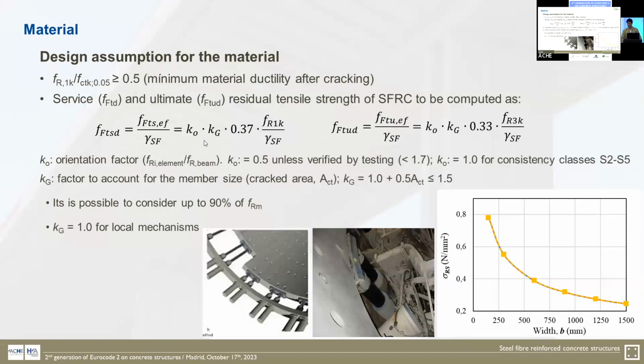And we also have to consider the orientation and the size factors, both for the serviceability and for the ultimate limit state. The difference here is this factor: for the ultimate limit state, we relate the resistance to the 2.5 millimeter crack mouth opening displacement value for FR3. The orientation factor is 0.5, unless it's verified by testing, and in any case never superior to 1.7. In the case of consistency classes S2-S5, it's suggested to be 1.0.